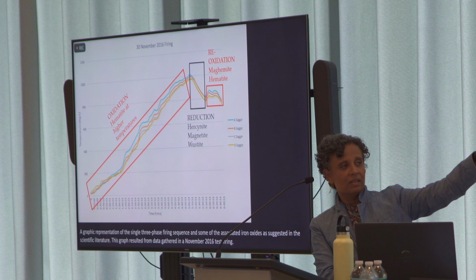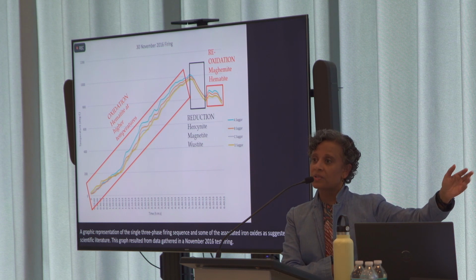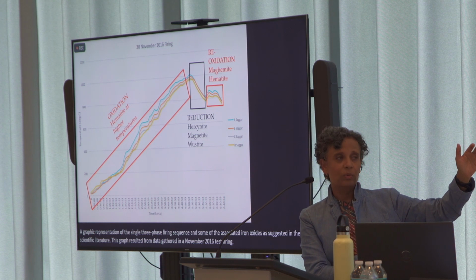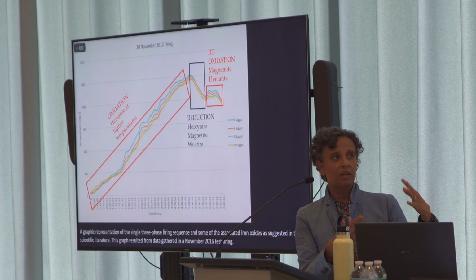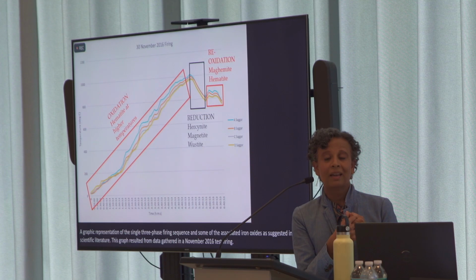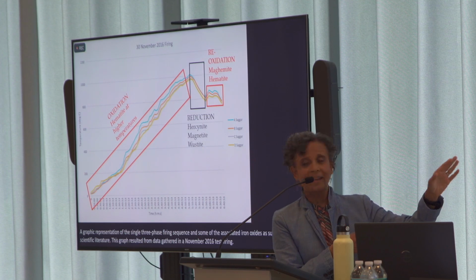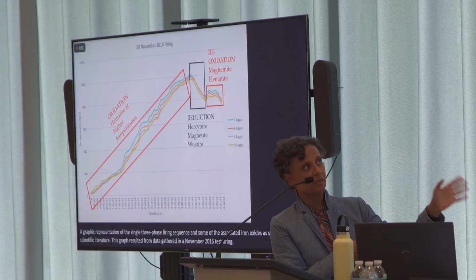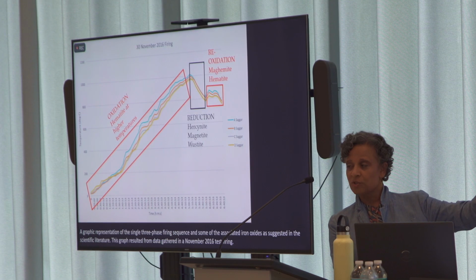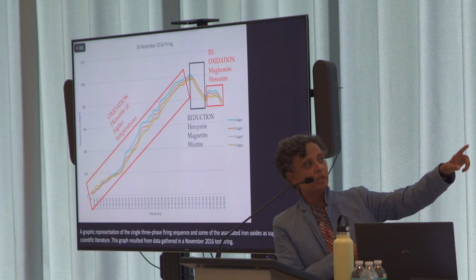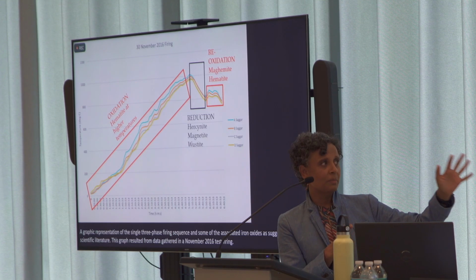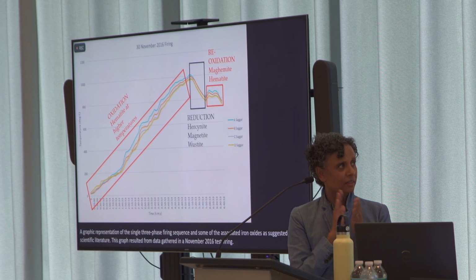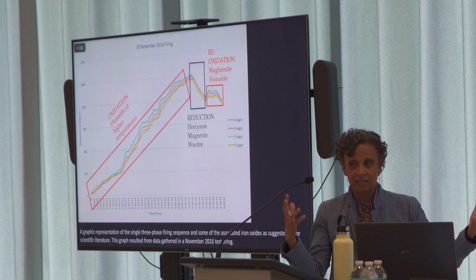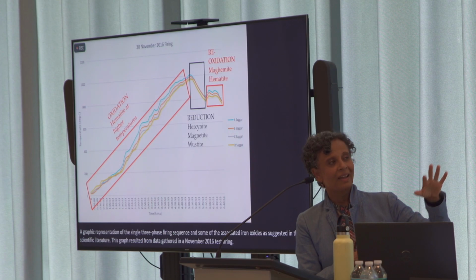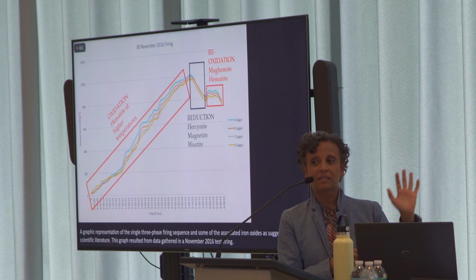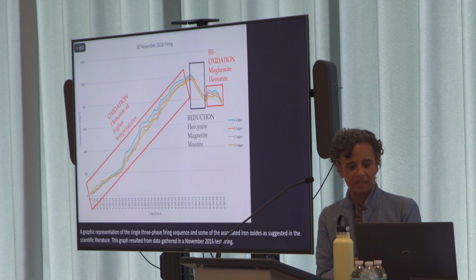At about 1,000 degrees, we closed all of the ports of the kiln and put the kiln into reduction. All the oxygen is being sucked out of the kiln and hopefully we're producing just those black iron oxides on every surface of all the pots inside the kiln. Then after about 45 minutes of that, we re-oxidized. We reopened some of those ports. Again, you have a thin layer of glass that has been created just on those areas that were painted, and everything else that wasn't painted goes back rather magically to being red.